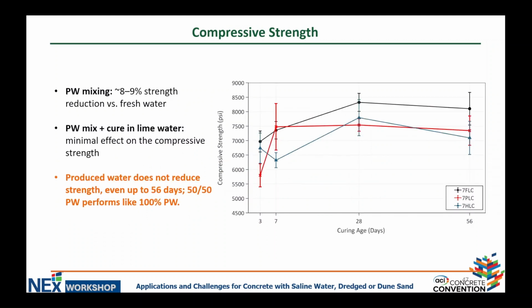Here we can see the compressive strength results for only the first three mixes. The three mixes are exactly the same, the only difference is the water: either fresh water, produced water, or a blend of 50-50 fresh and produced. So what we can see here is that produced water actually decreased the compressive strength slightly at different testing ages, on average an 8 to 9% decrease in compressive strength compared to the 7,000 mix that was made with the fresh water. Again, that decrease, 8 to 9%, is kind of acceptable in our industry, as we know. So it's not really that bad.